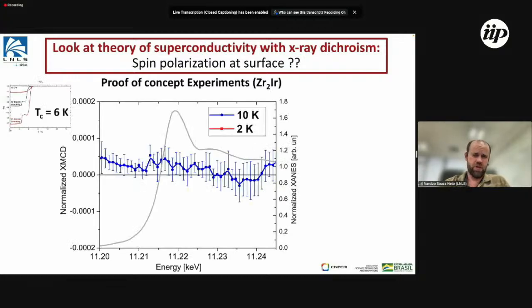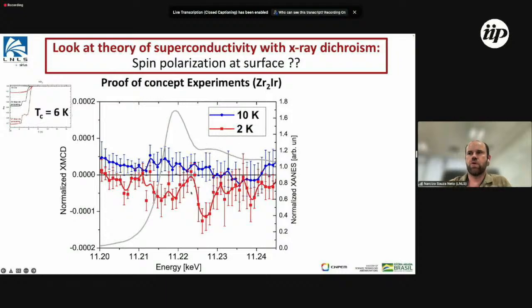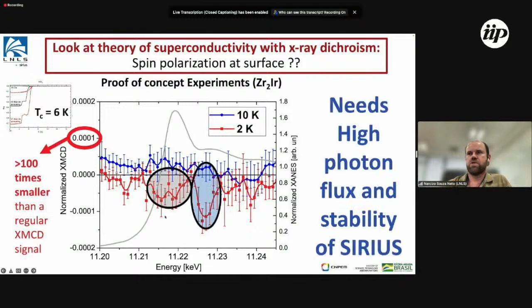Actually, we already did a proof of concept experiment in the old synchrotron. We are about to do a new experiment here two months from now. So in this material, when we are at 10 Kelvin, there is basically nothing within the error bar. But then when we go to 2 Kelvin, below the superconducting state, it seems to have, noisy, but two peaks here and here, that might be related to this dichroism. You still have to confirm. This would be related to the superconductivity in the iridium. But this high energy peak here would be more related to the hybridized electrons between the zirconium and the iridium. So that we have to confirm.